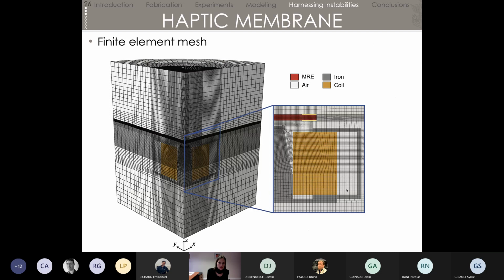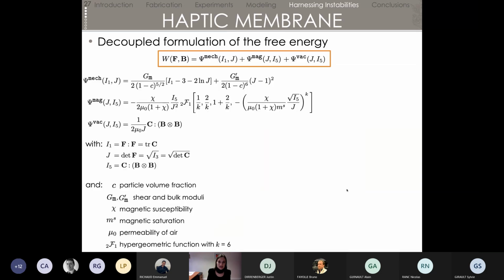There is also a lot of work that has been done on finite element on that side. So again, the big issue with these materials is that you have to mesh the air around it. So when you show the mesh, it's already something that's very expensive because you have the MRE layer, the iron core and the coil, as well as all the air really far away around your system. The only thing they gain is on the formulation of the free energy. So they're still doing phenomenological models, but here you still have your mechanical part, just in case you do not model any magnetics at all. You have your magnetic free energy and the vacuum one, because we also want to do one energy for the whole finite element mesh.